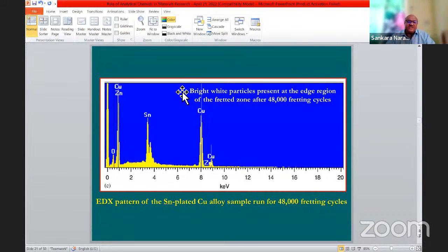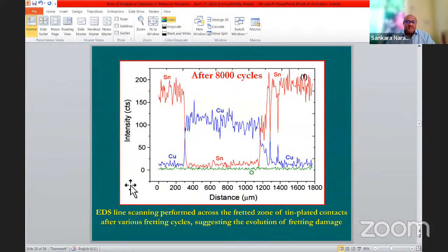We also took an EDX pattern at different regions. These are the bright white particles present at the edge region. At the edge of the region, you can see that there is a lot of tin and copper and oxide also there. This is another EDS line scanning pattern.